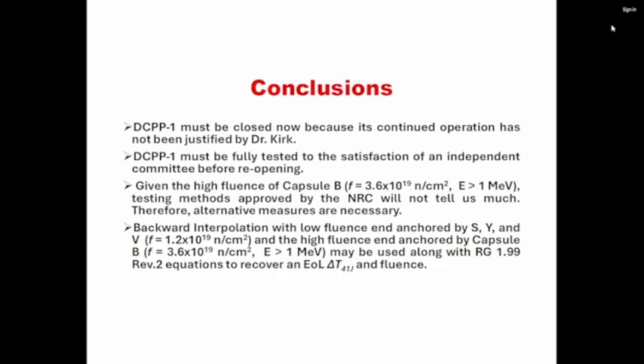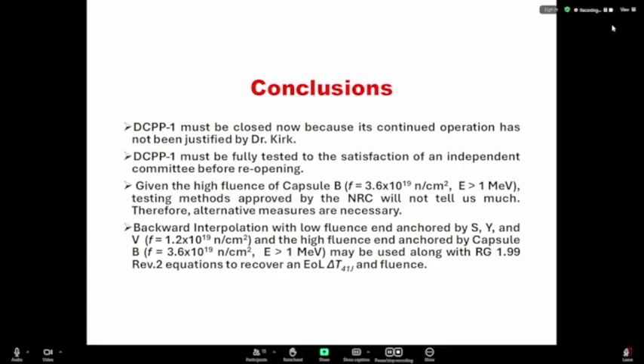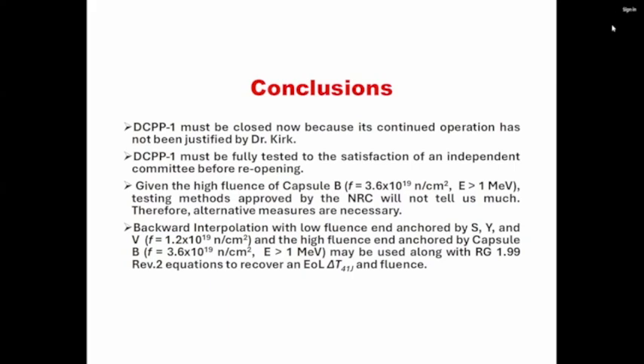So in conclusions, it's our position that Unit 1 must be closed now because its continued operation has not been justified by Dr. Kirk. It must be fully tested to the satisfaction of an independent committee before reopening. Given the high fluence of capsule B, 3.6 to 3.7 times 10 to the 19, depending on when it will be actually pulled, the testing methods approved by the NRC will not tell us much. Therefore, alternative measures are necessary.